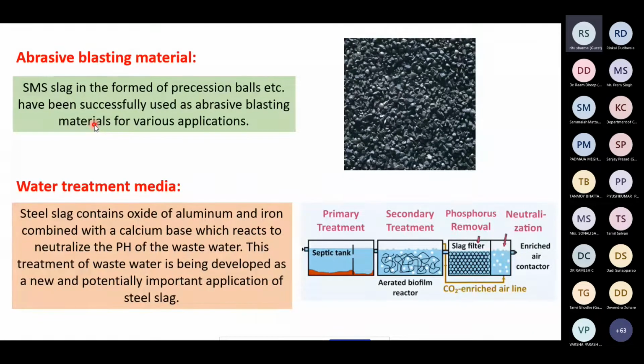Then abrasive blasting material. SMS slag, from the precision balls, etc., has been successfully used as abrasive blasting material. So blasting is done. Usually you have heard about ship breaking yards. They try to recycle the steel, but the steel of this ship is covered with a lot of paints and coatings. Now those paints and coatings must be removed before the recycling of the steel.